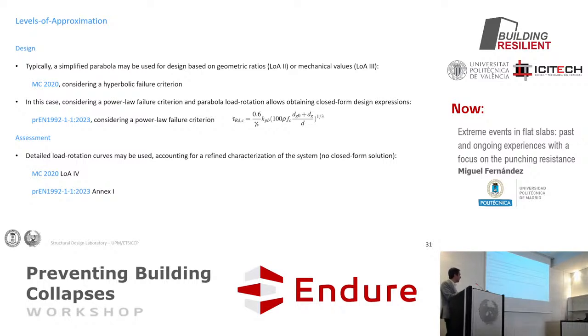Then, as you have to get the resistance, you have to solve iteratively. Not for design, but for assessment, you need to do that. In the next generation of Eurocode, there was a change in the hyperbolic failure criterion, changing it to a power law, and then you can calculate in a closed form manner what is the expression that you will get with the theory, and this is the equation that you will see in the code, which is not that far to what was before, but now it is derived from a theory, and that allows using in a very compact manner.